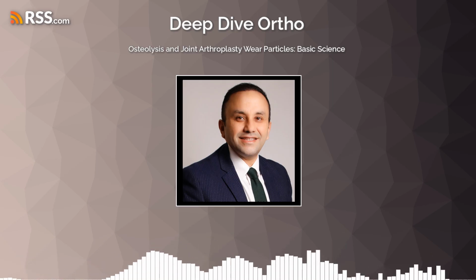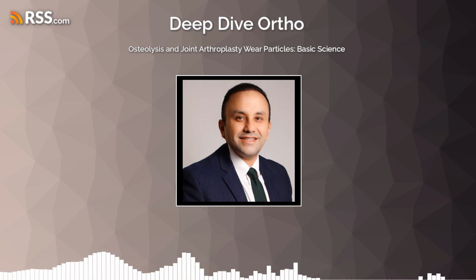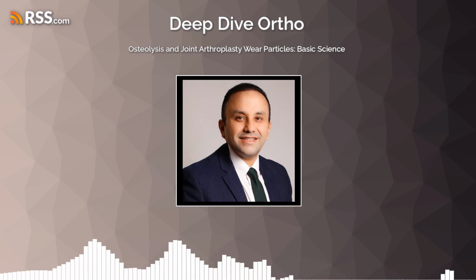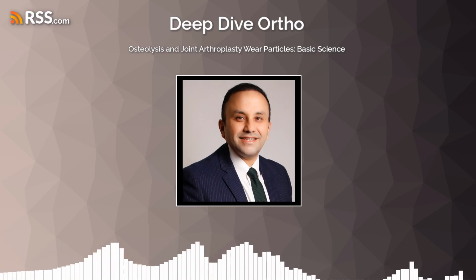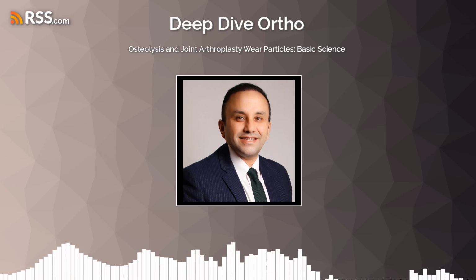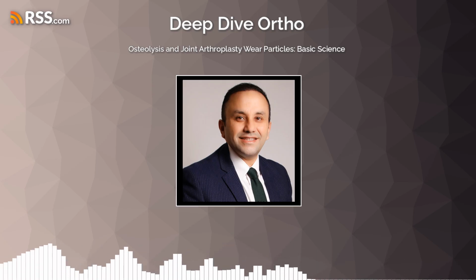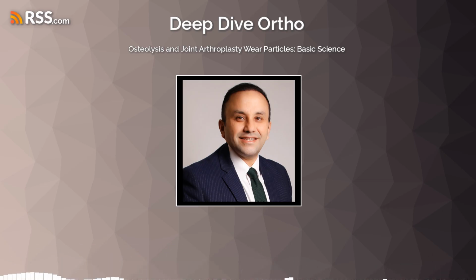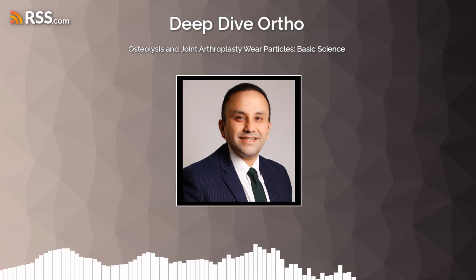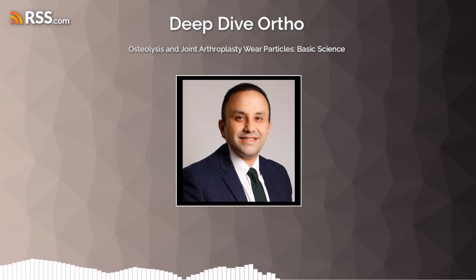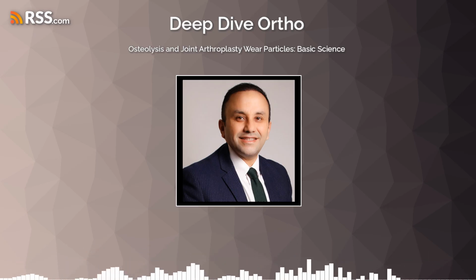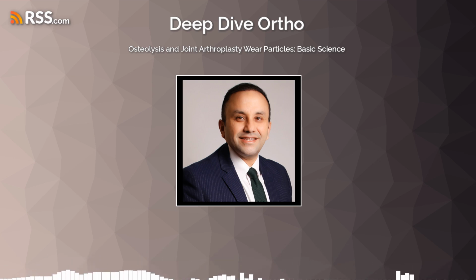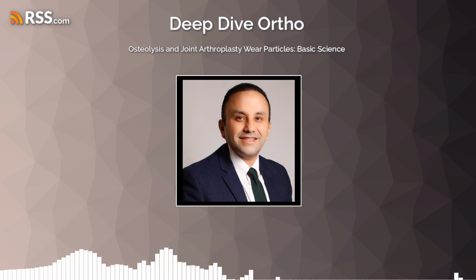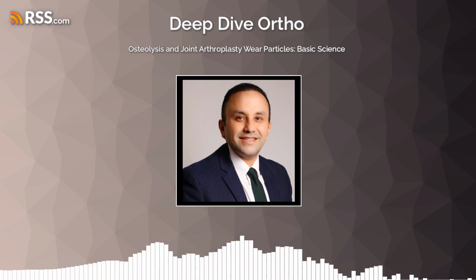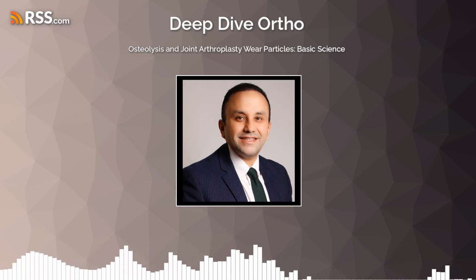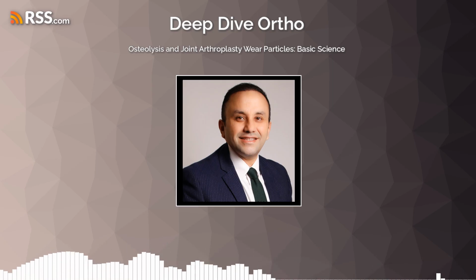What about improving the implants themselves? Hugely important. Advanced bearing surface designs are paramount and continue to evolve rapidly. This includes further development of ultra-high molecular weight polyethylene bearings with enhanced durability and wear resistance, like the next generation of highly cross-linked polyethylenes, some incorporating antioxidants like vitamin E for stabilization. Vitamin E. How does that help? It helps to quench the free radicals created during the irradiation process used for cross-linking, which can otherwise lead to long-term oxidation and degradation of the polyethylene, potentially increasing wear later on.